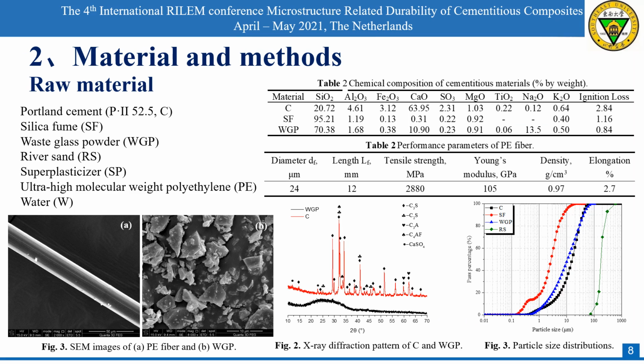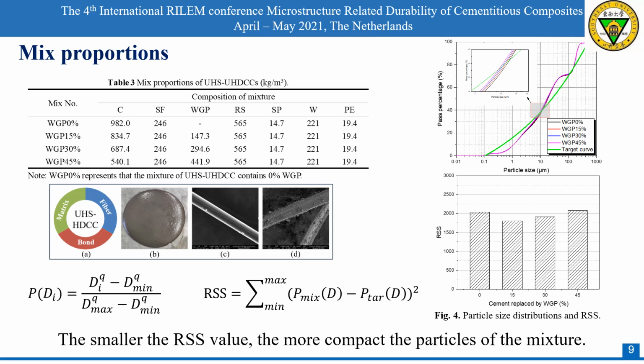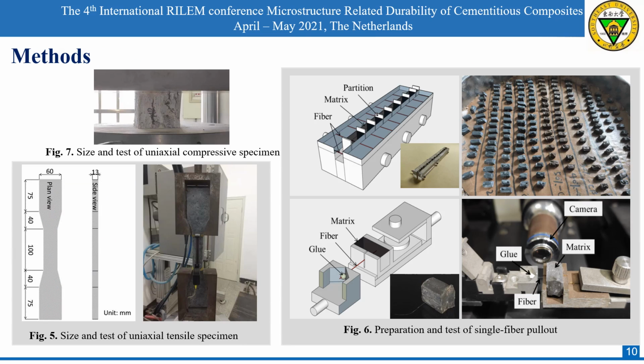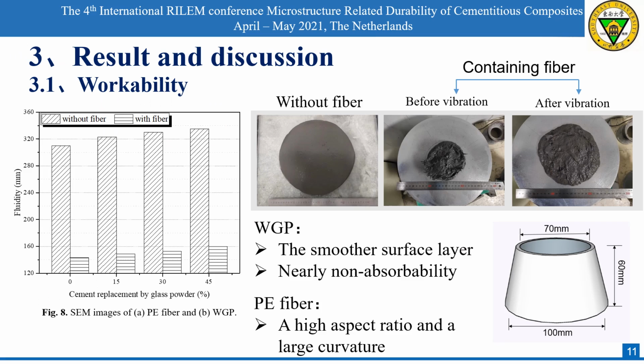Here are the characteristics of the raw material. The mixing ratio of the matrix is calculated according to the tightest packing theory of particles. The smaller the RSS, the more compact the particles of the matrix. This is the experimental test method, including compressive strength test, uniaxial tensile test, and single fiber pull-out test. This is the result and discussion.